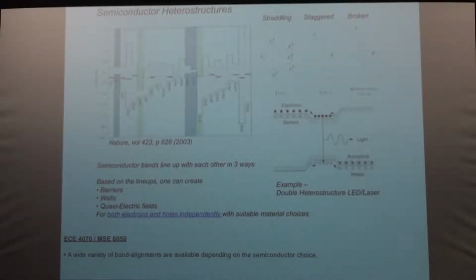So the vacuum level is when the electron has completely escaped the binding forces of the crystal. It's completely free now, and it's not tied to the crystal. Essentially, if I have an electron at the bottom of the conduction band of silicon, it has an energy that is about 3.8 eV below the vacuum. That's what it means, below the vacuum energy. So that's its stability. Just by heating a piece of silicon crystal, I have no chance of getting that electron to escape from the silicon crystal.